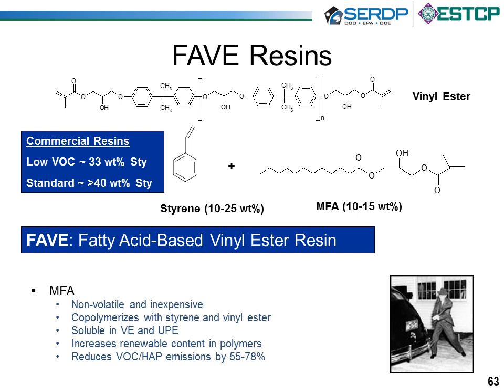In this work, we added the methacrylated fatty acids to reduce the viscosity of these vinyl esters. And we did have to use some amount of styrene in these resins, as I'll show you on the next few slides. But we were able to reduce that styrene content to 10 to 25%, and most commonly about 20 weight percent styrene. In all, this allows us to increase our renewable content in our polymers while reducing HAP and VOC emissions. Styrene is a hazardous air pollutant, so it's very important to reduce the amount of emissions from these resins as possible.